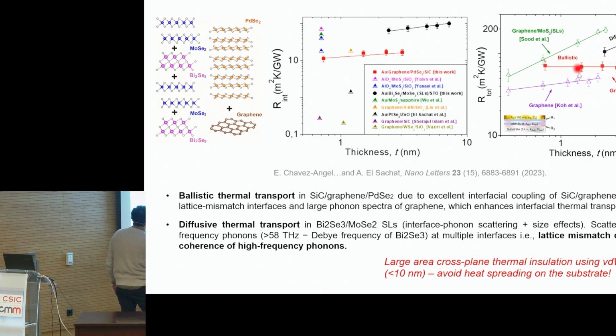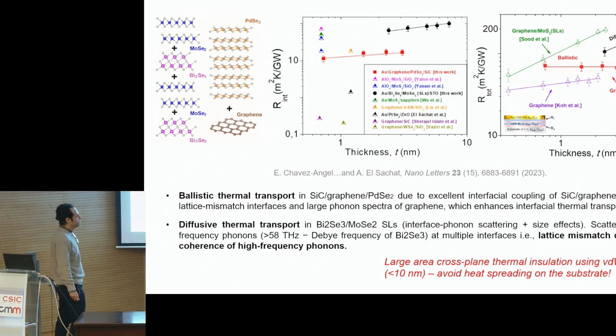So these are the superlattices that give us a high thermal resistance. So this is a way to control the heat propagation in the cross-plane direction, because these superlattices can be used as an active material in devices. If we manage to keep the long-range crystallinity of these materials, we can still have heat propagation in plane, but we kill the cross-plane. So that was the idea of this work.